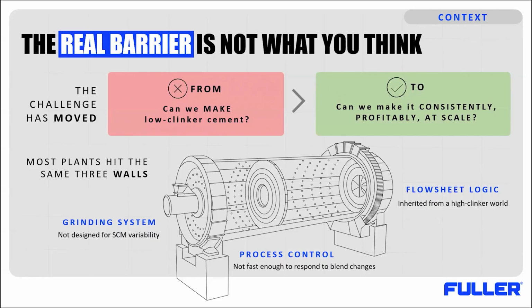The first wall is the grinding system. Many circuits were designed around clinker-rich cement, not high SCM variability. The second wall is process control. When moisture, loss on ignition, and fineness or reactivity change, the plant often reacts too slowly. The third wall is the flow sheet logic. Many plants still operate with layout, storage concepts, and quality loops inherited from a high clinker world. So the barrier is not only whether the material works. The barrier is whether the full plant system can keep quality stable while the material stream is changing.